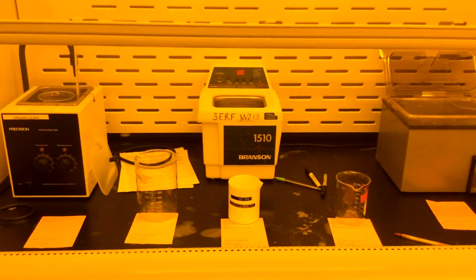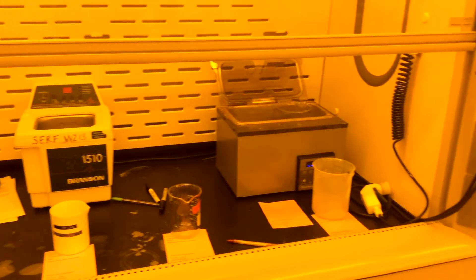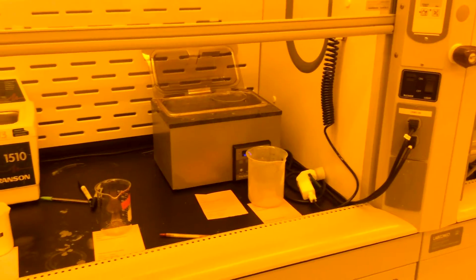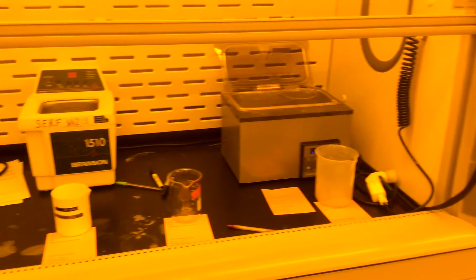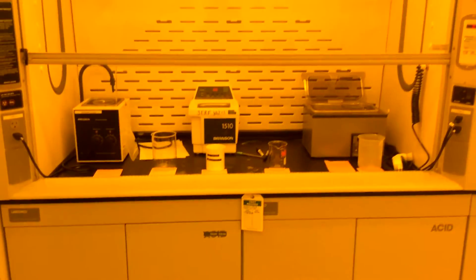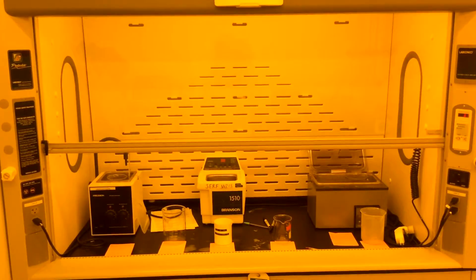It is often necessary to clean the wafers before performing certain procedures. The most thorough clean done in this lab is the RCA clean, which must be performed before any high temperature processing steps such as oxidation and diffusion. This clean involves submerging the wafer samples first in an organic clean solution for 10 minutes, then a dip in a hydrofluoric acid solution for 15 seconds, then finally submerging in an ionic clean solution for 10 minutes.